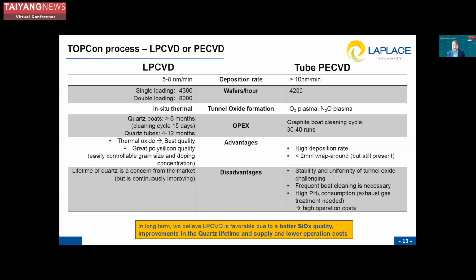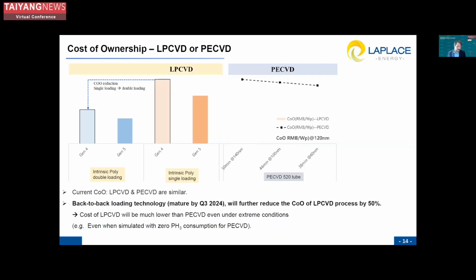On the LPCVD side, on the other hand, we have the thermal oxide, which has a very good quality and is very stoichiometric. And also the polysilicon is very easily controllable on the grain size and the doping concentration. But as mentioned, the quartz is a concern from the market, but we believe that in the long term, LPCVD is still favorable, mainly thanks to the oxide quality, but also as we can see in the market, a lot of improvements are happening for the quartz lifetime, and also on the supply chain, and therefore also on the lower operation costs.